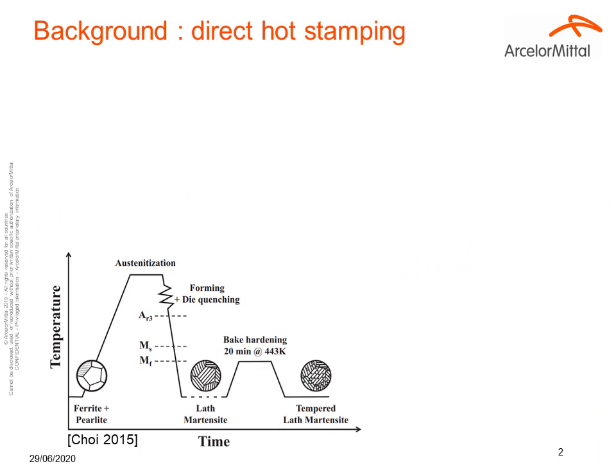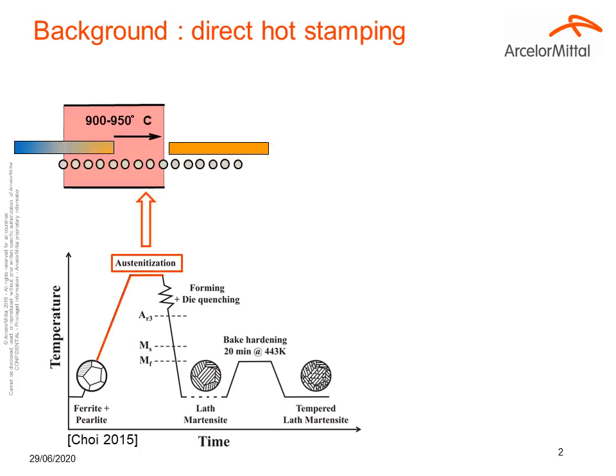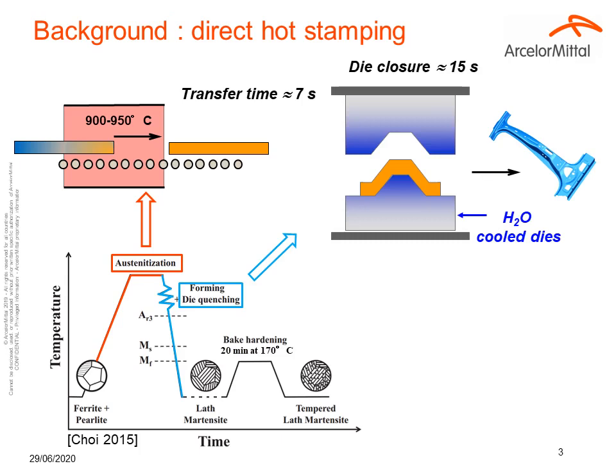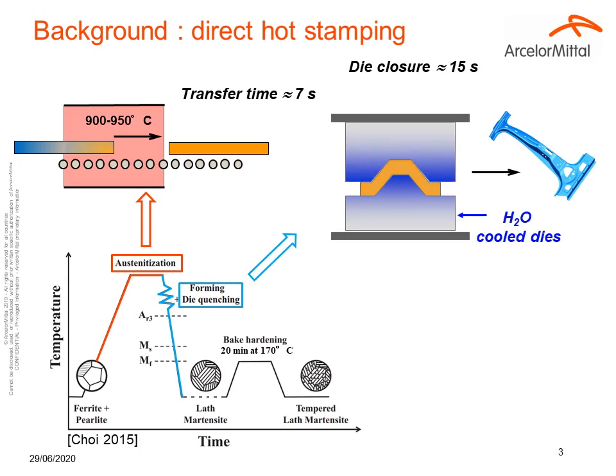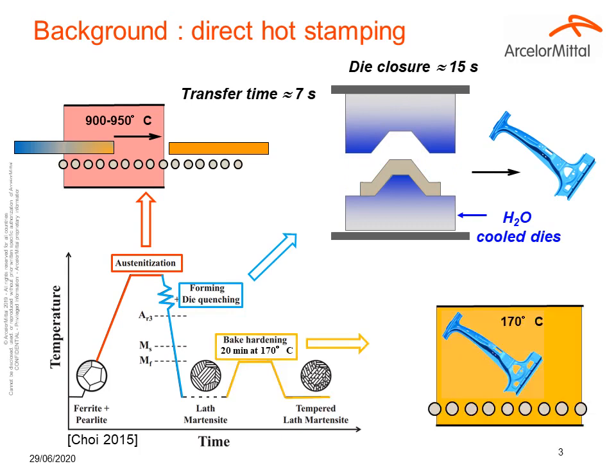Here is a classical representation of the thermomechanical treatment used for press-hardened steel and the corresponding microstructure at the different steps. First, the austenitization between 900 and 950 degrees Celsius. Then we realize, in the same step, the forming and the quenching thanks to the press, which is water-cooled. And third, the bake hardening process, which is a typical heat treatment of 170 degrees Celsius during 20 minutes.